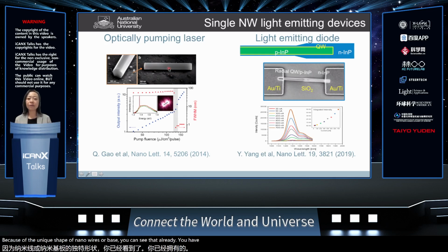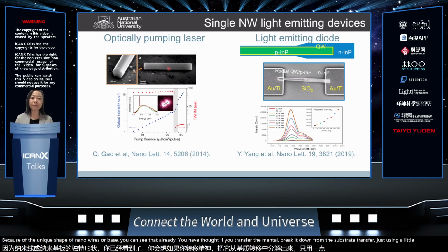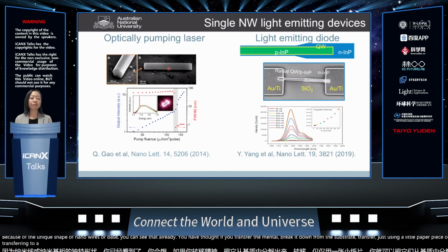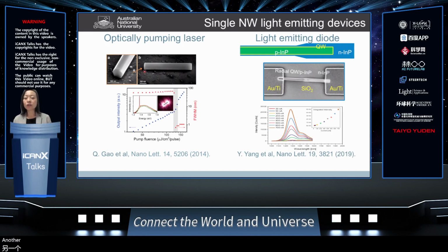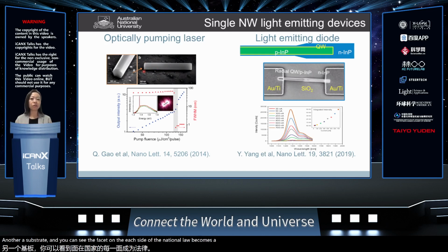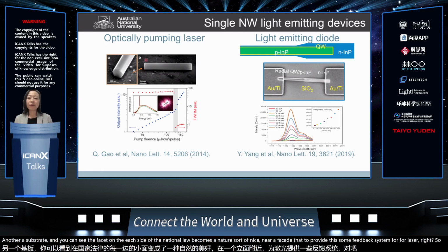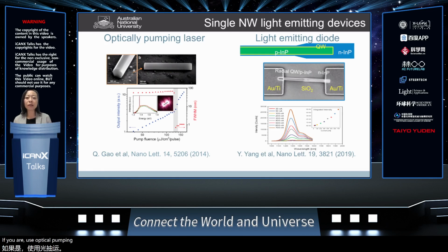If you break them down from the substrate just using a little piece of paper, you can transfer them onto another substrate, and you can see the facet on each side of the nanowire becomes a natural mirror facet that provides the feedback system for a laser, right? So if we use optical pumping, we can see this beautiful lasing coming from the facet, really showing that it's a really good material for light emitting devices.